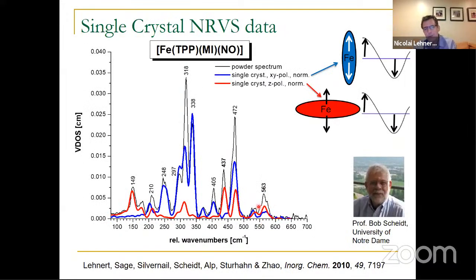And you can see here we have a mixed polarization. So this vibration has contributions from in-plane and out-of-plane motion. And what that means is that essentially the ion, if this is the plane of the heme, the ion doesn't move like this or like this. It kind of moves diagonal. So the ion moves a little bit out of the plane of the heme, and that means we have some intensity in this out-of-plane polarized spectrum, some intensity in the in-plane polarized spectrum. Okay. So that's pretty good.